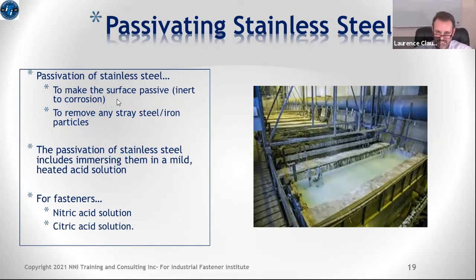All right, so passivating stainless steels: again, we want to make them even better than what they are in their as-made condition. And so to do that, we increase or boost the inertness of the oxide coating on the top of the parts. And that is done by passivation. Passivation means to make it more passive, more electrically inert. We do that in a heated bath. With fasteners, we do that generally in a heated bath of nitric acid or citric acid. Those are generally mild acid solutions.